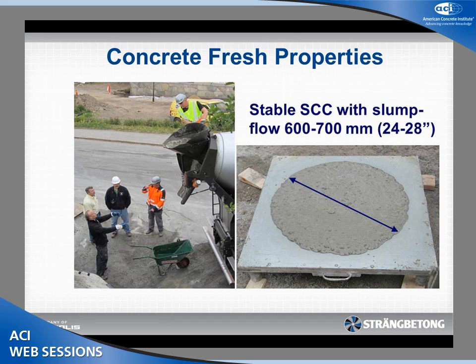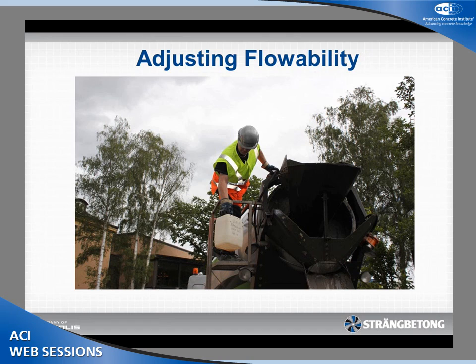We also had to decide on the concrete. SCC can range from slightly more than 400 millimeters to over 800 millimeters slump flow, but we wanted slump flows between 600 and 700 millimeters — between 24 and 28 inches — and stable. When you have half the world's experts in Stockholm for four days, you don't want to jeopardize too much. So basically, the concrete delivered was slightly stiffer than we wanted, and we had to adjust each mix differently.